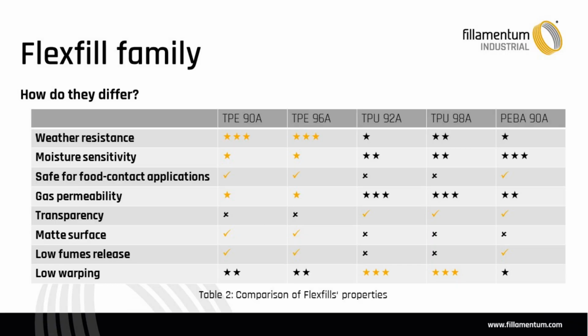Regarding the moisture sensitivity, you can see that PEBA, because it's based on polyamide, has very high moisture sensitivity. I have already mentioned in our first webinar on tricky nylons that nylons are very sensitive, and when you don't dry the filament, it starts degrading under the melting temperatures, and you will have different mechanical properties, different chemical resistance, and you won't achieve the properties you need.